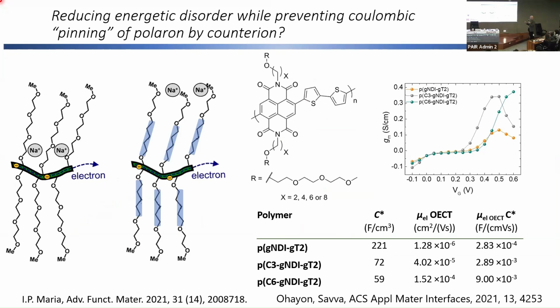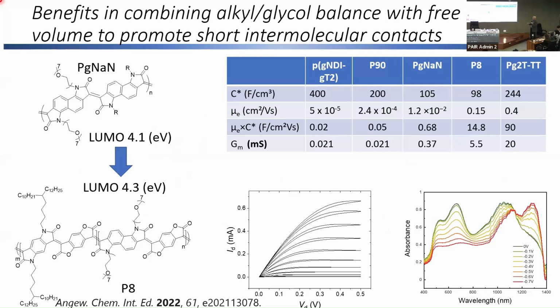Other ways we can reduce the swelling is by having not only alkyl chains on the repeating units, but each chain could also have part alkyl and then part glycol. So you push the glycolation away from the backbone, and when you do that, you can introduce more order along the backbone area, and that reduces the ability for ions to penetrate closer, which seems to help. Other things we can do is, again, combining interdigitation through the alkyl chains, as well as having these very stiff materials, which is a way again to help reduce this disorder. And all of these factors lead to an improvement in properties.